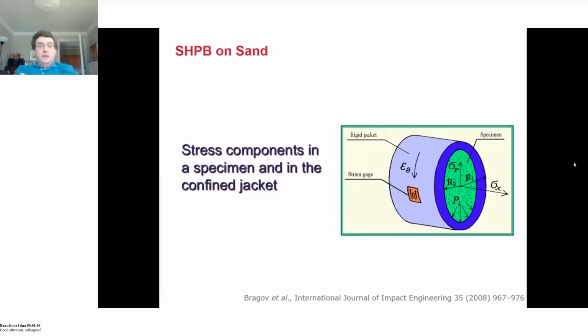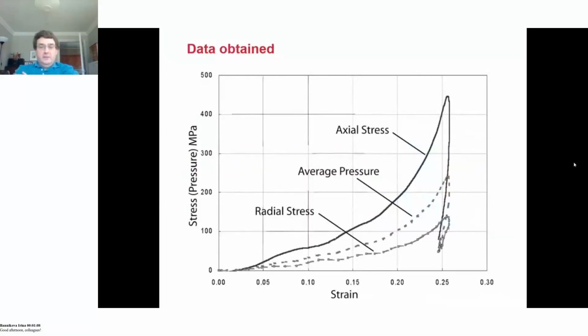Therefore, you can use the strain on the outer surface in order to get a good measure of the stress on the inner surface of the jacket. And this is the kind of data you can obtain from a Hopkinson pressure bar, showing the stress, in this case, in megapascals.